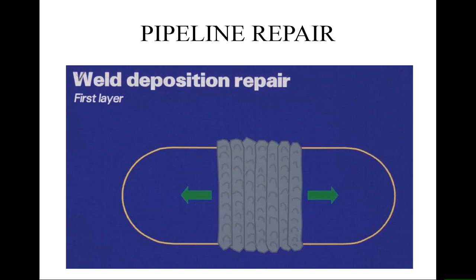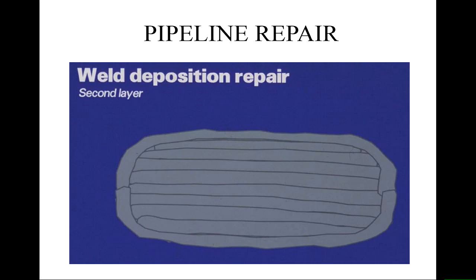So you have the first layer of weld where you start in the middle of the repair and then you weld outwards. So you do a pass in the middle and then two welders can start to weld away from that central pass to the ends. And then you tend to weld perpendicular to that along the length of the weld. And when you've got enough layers, you will put a weld around the outside to make sure that everything is tied together properly. And you might have to do that 2 or 3 times depending on how deep the defect you're welding, but usually there's only 2 passes.